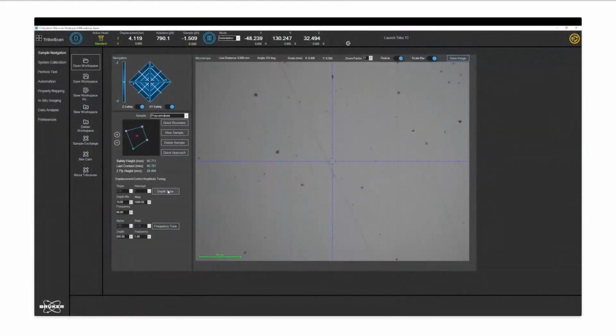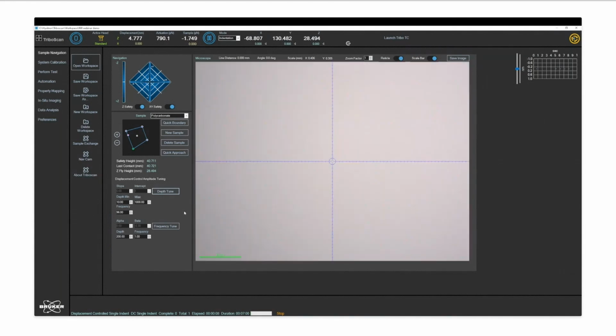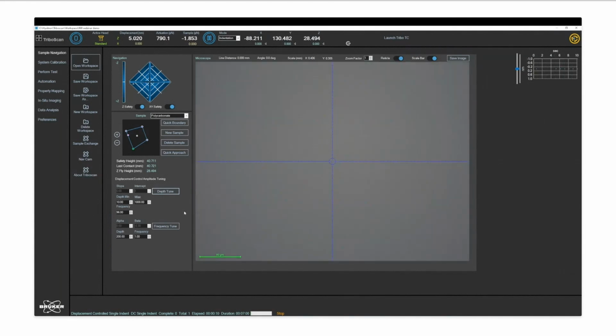In order to automate the AC force setting, we are going to run an indent that tunes the force amplitude using a displacement set point. This measures the stiffness response and sets the correct amplitudes with a feedback routine. So we'll start by selecting the sample and clicking on this depth tune button here. This is going to be on the polycarbonate sample.